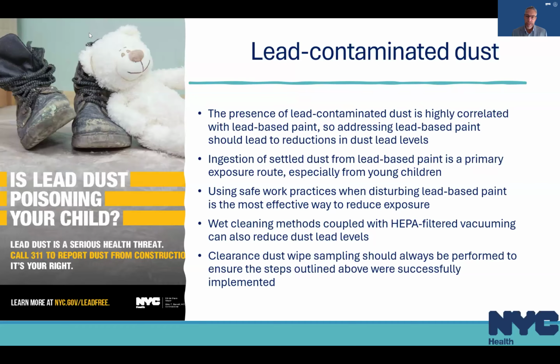What's the source of the lead contamination that's being found in the dust? For the purpose here in New York City, we generally assume that if you're finding lead-contaminated dust in the home of a child, the best approach to address that is to get rid of the lead-based paint. Absent the ability to remove the lead-based paint, then you can use wet cleaning methods coupled with HEPA filtered vacuuming to reduce dust lead levels. But without addressing the source, those levels may start creeping up again. And as I previously mentioned, if you're going to disturb lead-based paint, you need to do clearance dust wipe sampling. And even if you're cleaning lead-contaminated dust, you should perform clearance dust wipe sampling to ensure that the cleaning was done properly.